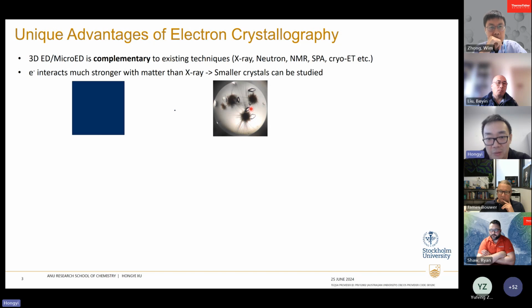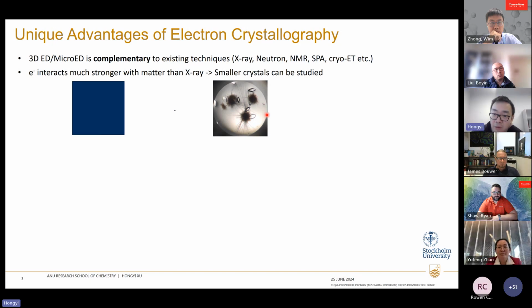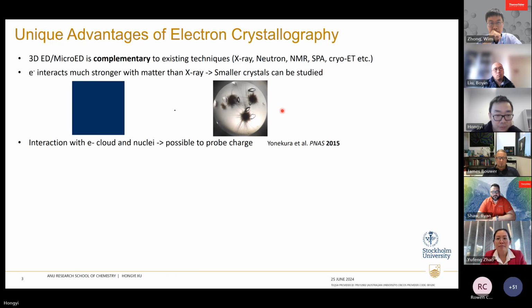In the protein world, you usually grow these proteins in the drop, and then these large, nice, pretty crystals are the ones you're looking for single crystal diffraction measurements at synchrotron, usually. And then these needle-shaped small crystals are actually perfect for MicroED. So about 30 to 40% of the plates you used to throw away contain crystals that might just be suitable for doing MicroED.